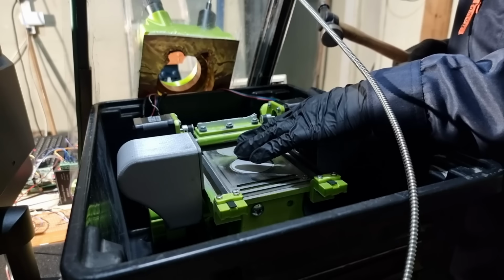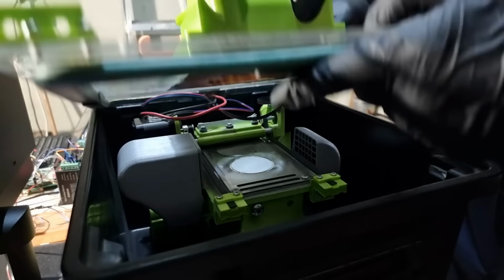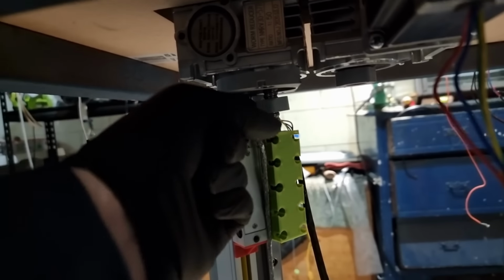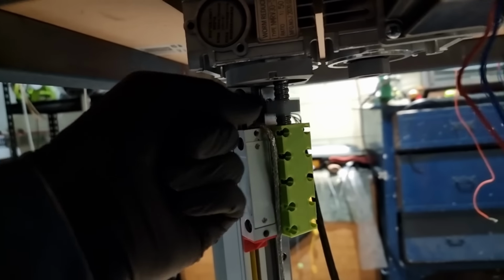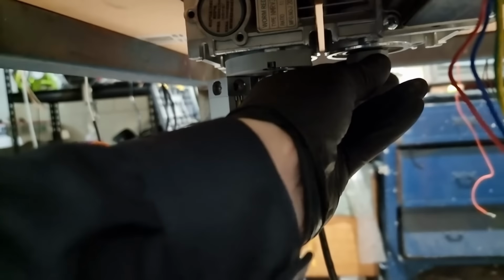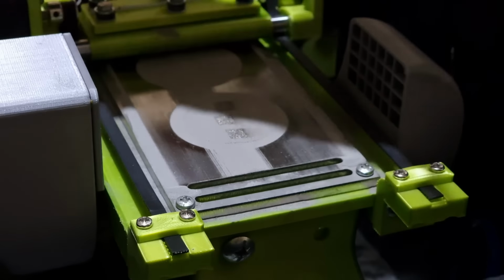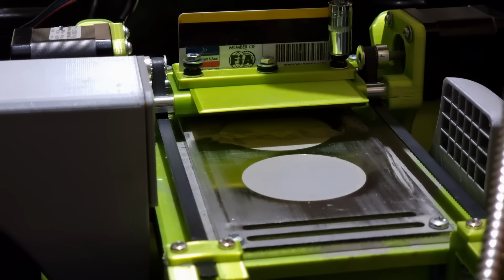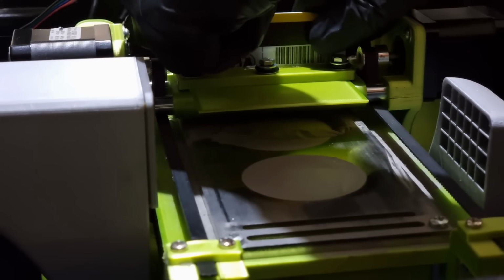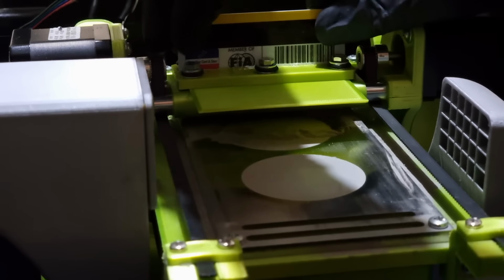I would persist with it for a little while as initially it wasn't too bad, and it would be a nasty job to deal with while I was already busy playing whack-a-mole with the other gremlins. I would come back to it later though. The plastic edge of the recoater blade was also suffering as the printed surfaces were eating away at it during every pass. This design would hang around for a bit longer than I would have liked, but was easy enough to replace even if it did slightly compromise the layer height.